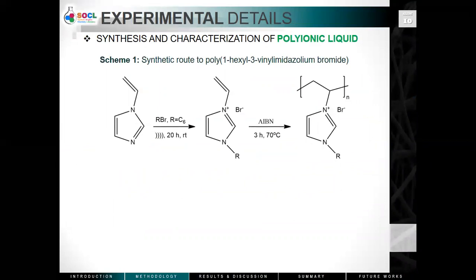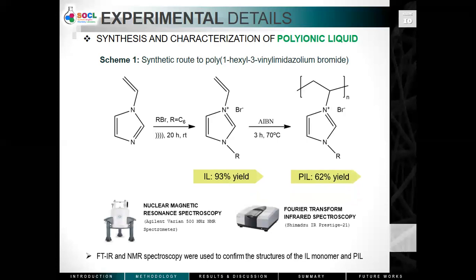The ionic liquid monomer was obtained through a solvent-less sonochemical synthesis that involves direct quaternization reaction between N-vinyl imidazole and N-bromohexane. The reaction occurs via SN2 mechanism with the conversion of tertiary amine to a quaternary ammonium salt through the alkylating agent N-bromohexane, which proceeds through a bimolecular nucleophilic substitution. Meanwhile, the synthesis of PIL was done through free radical polymerization initiated by AIBN that was purged under nitrogen atmosphere. The free radical polymerization was employed because it often yields polymers with controlled molecular weights. The final products obtained have 93 and 62% yields and were characterized to confirm the structures.